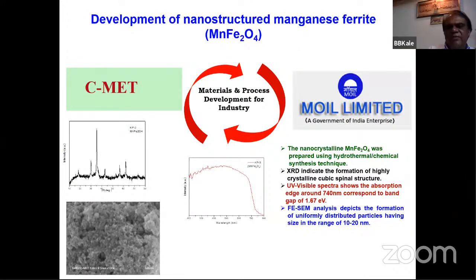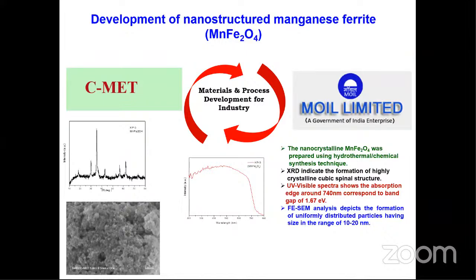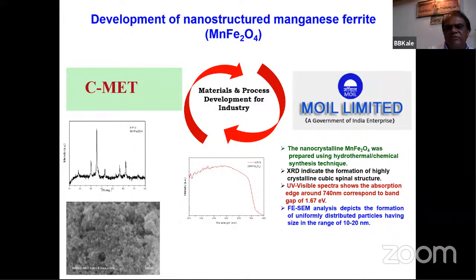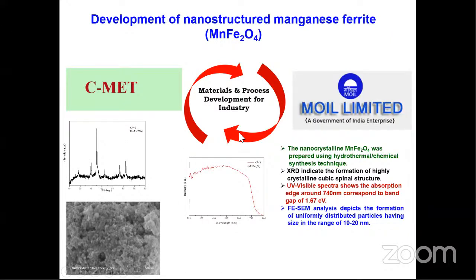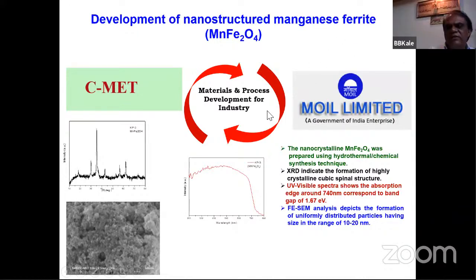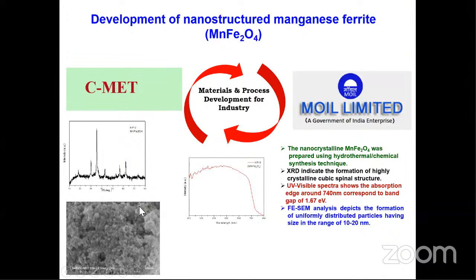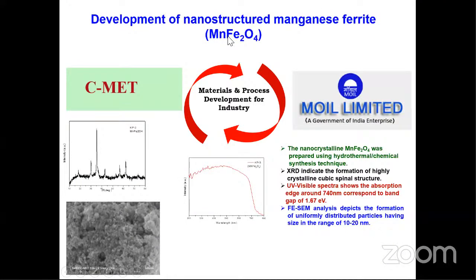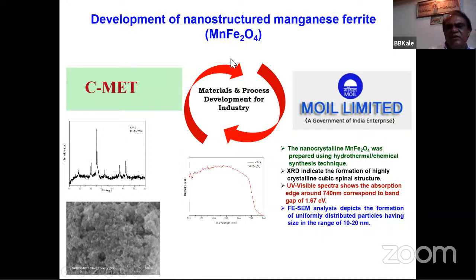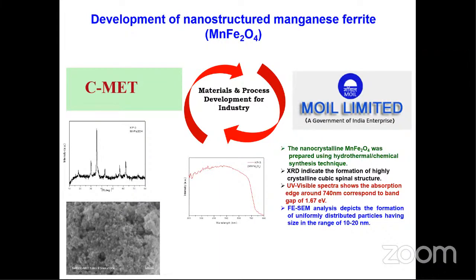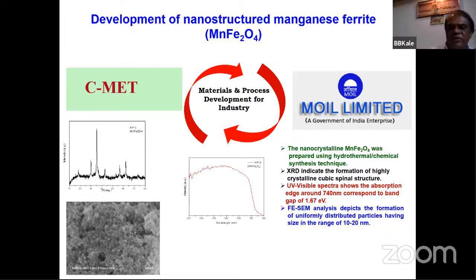Then Manganese Ore India Limited, MOIL India Limited, they have manganese mines. 75 mines are owned by MOIL India Limited in Nagpur, around Madhya Pradesh. So they have a lot of manganese sulfate waste, because during leaching this manganese sulfate comes out, and we used this manganese sulfate and gave them ferrite manufacturing technology. We made the ferrites for them, with composition using manganese and iron oxide, also with their iron oxide coming from their waste. And now this project is already completed. Now we are getting 3 more projects from MOIL, making some value-added compounds for them.